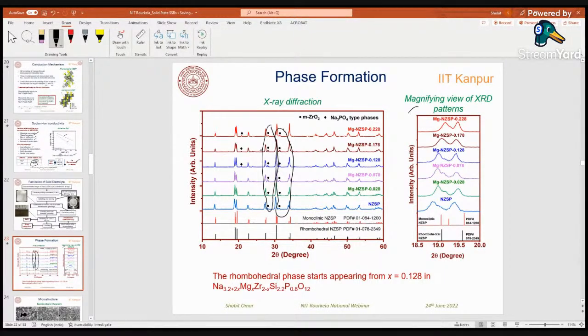But you can also observe that from 0.128 onwards, you have some small peak of Na3PO4 phase. This phase also contains some magnesium, because this has been reported earlier as well. Now come to this figure.